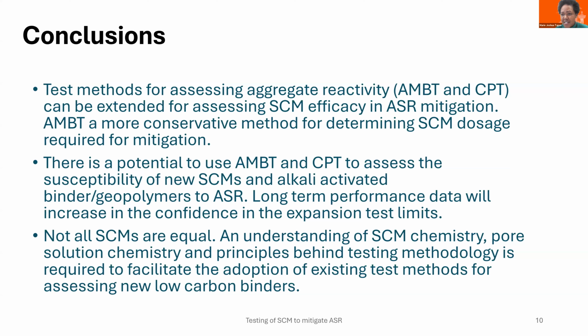Is there a potential to use the test methods for assessing the new generation of SCMs and low alkali binder systems? I think certainly there's a potential to do that. At the bare minimum, at least for a comparative assessment, of course, the test limits probably will need a little bit more work. And again, the long-term performance data will increase the confidence in these expansion limits. I think it's critical that we understand the test methods for us to be able to decide. I think that goes for any other accelerated test methods that we'd like to apply for assessing the new generation of low-carbon concrete.